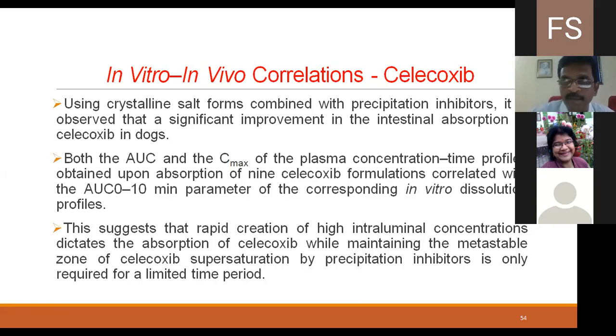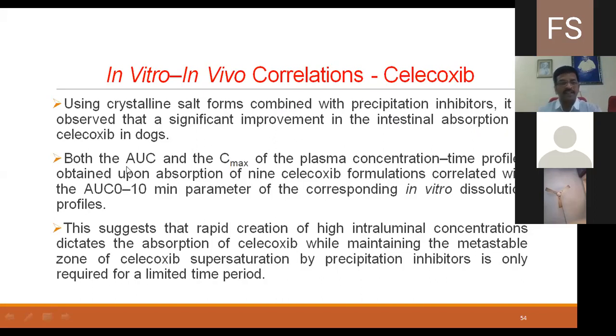See, this celecoxib example is interesting. A crystalline salt form of celecoxib combined with precipitation inhibitors showed a significant improvement in the intestinal absorption of celecoxib in dogs. When AUC and Cmax were recorded upon absorption of 9 celecoxib formulations, they correlated well with the AUC value corresponding to the in vitro dissolution profile. So when in vitro studies were carried out, and then in vivo studies for 9 celecoxib formulations in the presence of this PPI, there is a relation and there is a correlation.